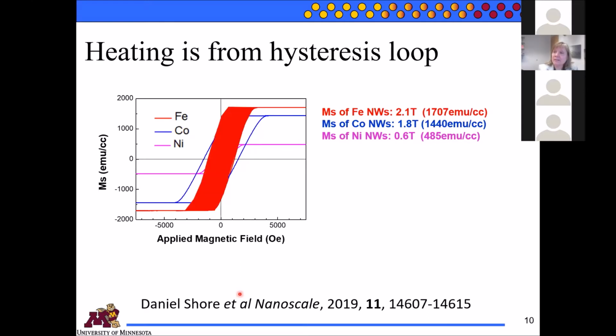So a couple things come into play then. How do you increase the area of this loop? Well, if you have a very high MS, you have a high area, and you might want a large coercivity, but you might not, and I'll show you that later. One thing we would really like though is, this is actually a measurement of an array of nanowires. The individual nanowires, we would like them to switch at a single field so that we have very tight control over the switching of each particle. And that's something that we're working on.